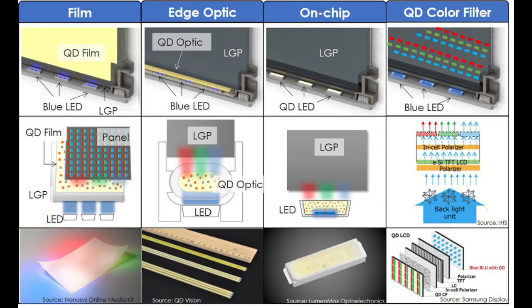Yeah, so the on-chip column there, the third one over, is basically moving these quantum dots instead of away from the LED, putting them directly on top of the LED. And so here you see the blue LED with the quantum dots that are actually in the LED encapsulant, which is typically a silicone type material. It's an optically clear material that is pretty robust to high heat and light flux. And so you have these quantum dots that are inside that silicone directly on top of your LED, and then that gives you your color conversion.